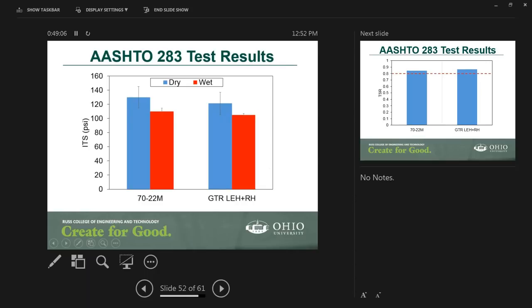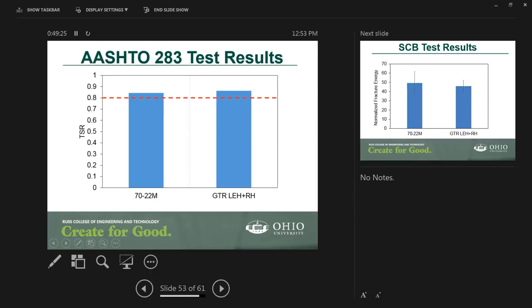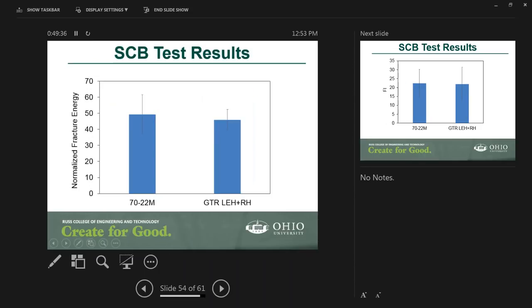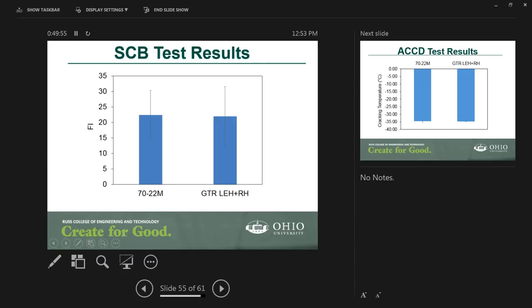For core samples, indirect tensile strength for both dry and wet, there was really no difference between the GTR and the polymer modified. For the TSR values, again, they were higher than 0.8 for both cases, the polymer and the GTR, and they were very, very similar. The SCB test, which was different than the Columbus, here they were much more similar. The GTR was slightly lower, but statistically it was not different in terms of the normalized fracture energy. In terms of the flexibility index, it was the same as the polymer modified 70-22.